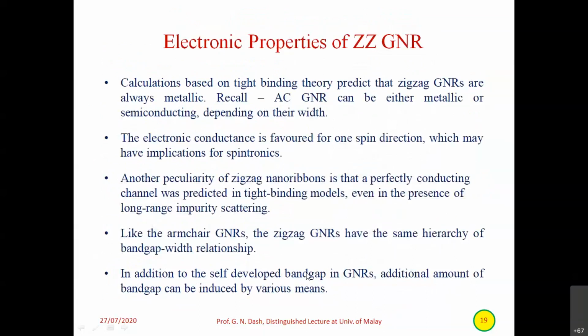Now, electronic properties. Calculations based on tight binding theory predict that zigzag nanoribbons are always metallic. Recall that armchair GNR can be either metallic or semiconducting depending on their width. The electronic conductance is favored for one spin direction, which may have implications for spintronics also. Another peculiarity of zigzag nanoribbons is that a perfectly conducting channel was predicted in tight binding models, even in the presence of long-range impurity scattering. Like the armchair GNR, the zigzag GNRs have the same hierarchy of band gap width relationship. We'll just see further about it.